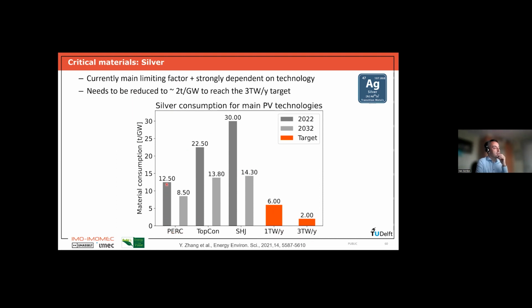Now, the amount of silver that we actually need really depends on the different technologies. Here, the dark gray is the amount of silver currently used per gigawatt for PERC, for TOPCon, and for silicon heterojunction. And the light gray is the prediction of the industry of how much they will need by 2032, with some improvements. We see that none of these technologies is reaching this low value, so we still have a lot of work to do. But PERC is typically doing much better at the moment than TOPCon and silicon heterojunction.